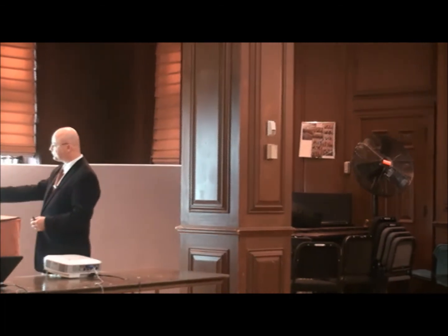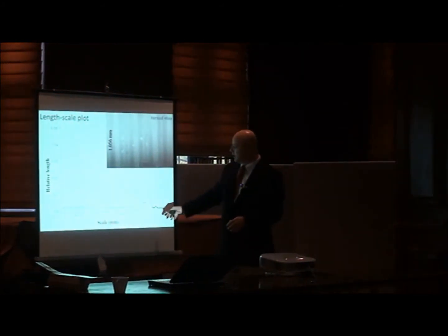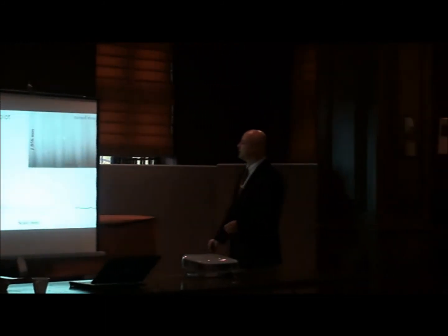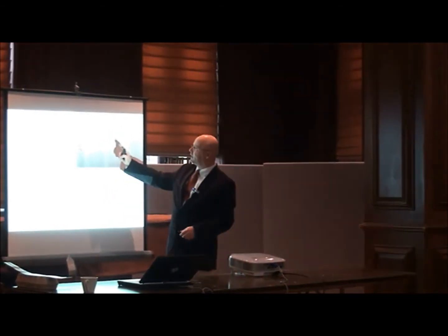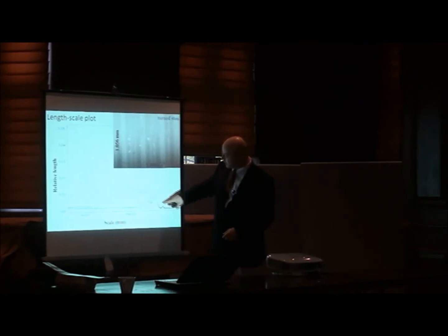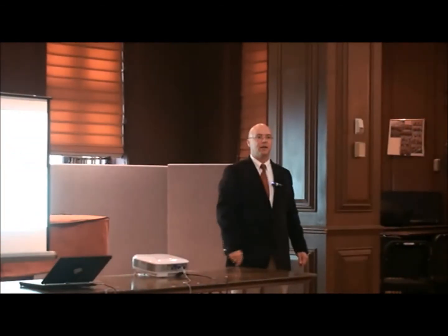And when we do that, if you plot the length of the dividers, which we call the scale, versus the relative length, the projected length, on a log-log plot, you get a graph that typically looks like this. This one is kind of special. This is actually a turned surface in steel, so you can see there's a periodicity in the surface. These local peaks along here are factors of the period on the surface, so we can find the periodicity on the surface. If that's all you care about, use an FFT analysis. But it's an artifact in here.